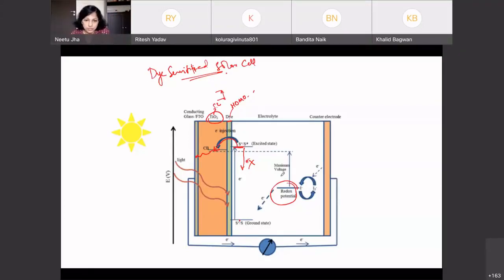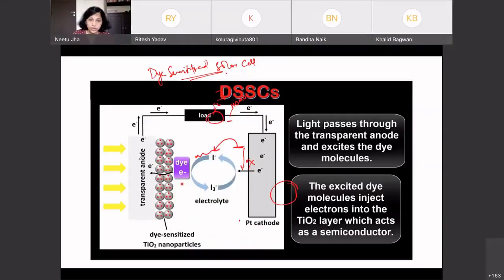Now, instead of this TiO2 coating on FTO glass, if we use TiO2 nanoparticles, then the performance goes up multiple times, because TiO2 nanoparticles have high surface area. High surface area can absorb a large number of dye molecules, and then obviously you can also play around with the band gap of TiO2, and because a large number of dye molecules are there, the fill factor and efficiency of this device obviously goes up.